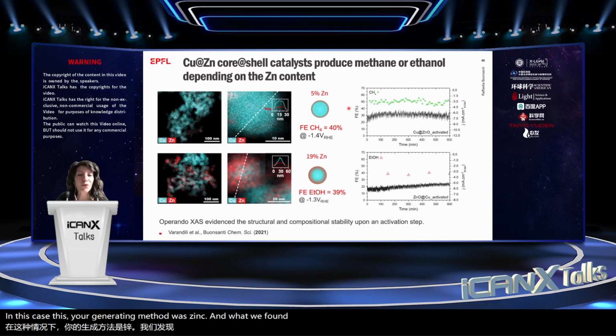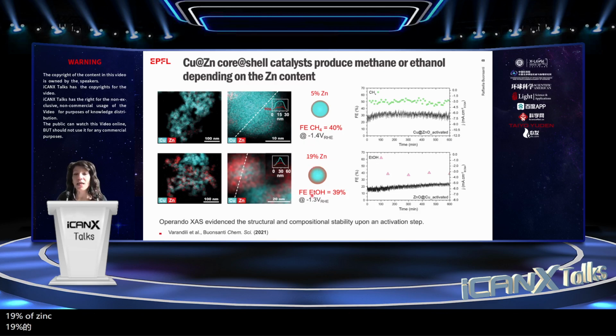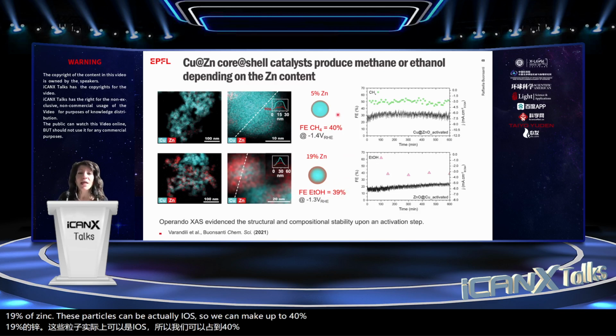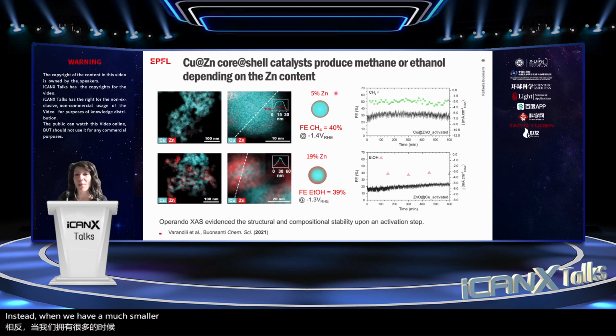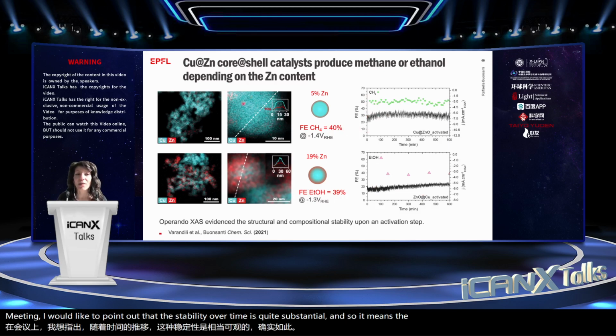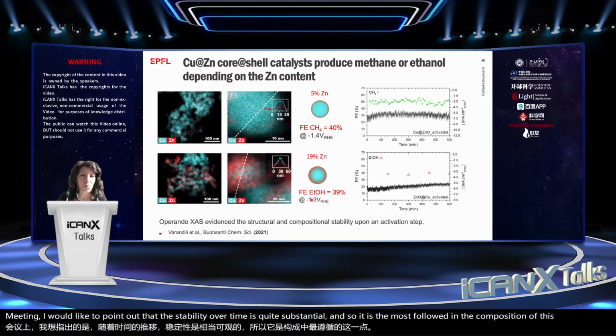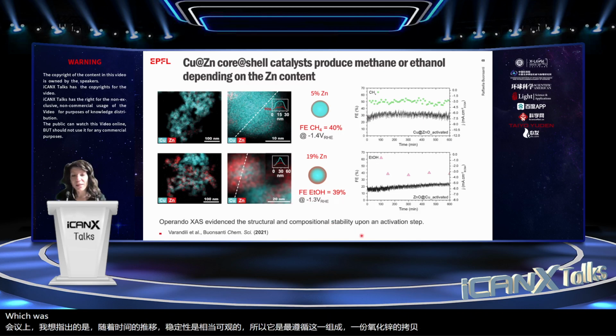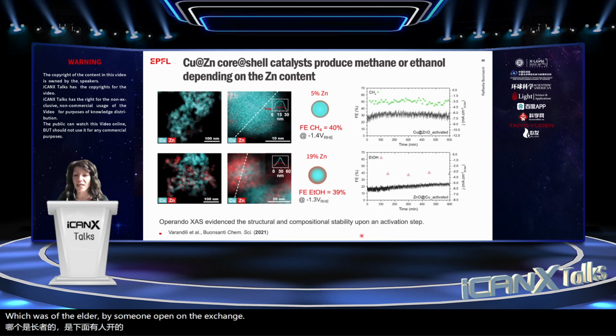And what we found in this case is that when we have these core shell particles with an alloyed interface containing 19% of zinc, these particles can be actually highly selective for ethanol. So we can make up to 40%. Instead, when we have a much smaller amount of zinc, these particles make only methane. I would like to point out that the stability over time is quite substantial, and so is the morphology and the composition of this copper zinc oxide, which was revealed by some operando X-ray spectroscopy study.